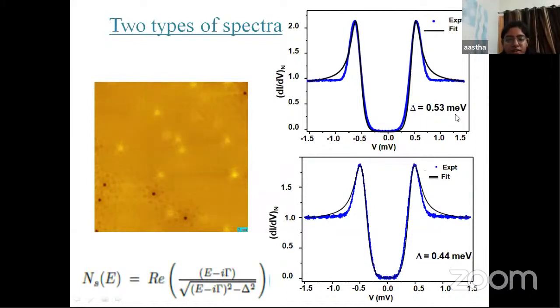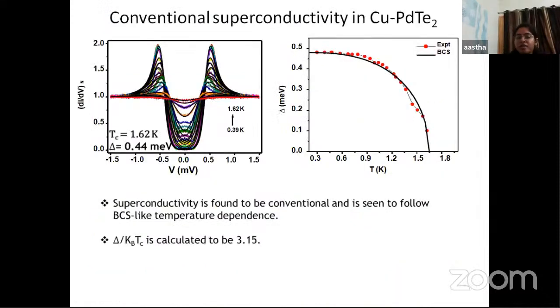For one of the spectra, the superconducting energy gap was found to be higher, 0.53 millielectron volt, while for the other case it was 0.44 millielectron volt. But in this case also, the superconducting energy gap is higher than what is observed for PdTe2, which is 0.32 millielectron volt. So we can say that the effect of intercalation is everywhere. When we look at the temperature dependence of the spectra with the lower gap, the spectra evolve smoothly with temperature, and finally the spectral features disappear at a critical temperature of 1.62 Kelvin, which is the critical temperature of PdTe2.